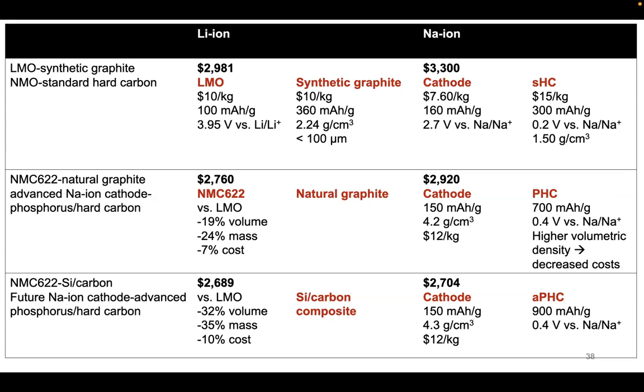So there are some decreases in cost of the active material, but in terms of the overall cost, the new electrolytes that have to be synthesized, the cost of NaPF6 in equivalent carbonates of the solvent in the electrolyte, the cost does go up a little bit. And even though, let's say, for hard carbon the capacity is a little lower, you have to use a little bit more of the material to have parity with the overall capacity at 300 versus 360 milliamp hour per gram. So all these offsets are taken into account when calculating the overall cost of the entire cell, not just the active material itself. So in the future, there is potential for pretty close parity between lithium-ion batteries and sodium-ion batteries.